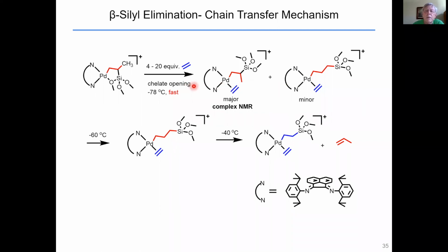And we see a major complex in which this chelate is simply opened and we trap ethylene. We see a minor complex where the C3 unit is linear. Now, if we warm this to -60 degrees, everything converts to the minor isomer. And so that must be a case where silicon beta eliminates to give the propene complex and re-adds to generate the linear structure. If we warm this up to -40, propylene is eliminated. Remember, we're in the presence of excess ethylene. Propylene is eliminated, and we end up with this ethylene complex with a C2 linker.